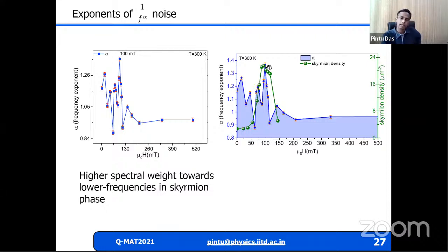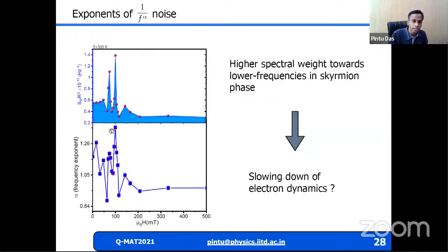And that tells us that the spectral weight towards the lower frequencies is increasing in the skyrmion phase. I'm plotting it here again along with the noise data. At the sharpest peak here in the skyrmion phase, we see that the frequency exponent is highest. That tells us that the low frequency weight is more in the system, and this means that the electrons are slowing down in the skyrmion phase. So this is the information that you get from the noise studies.